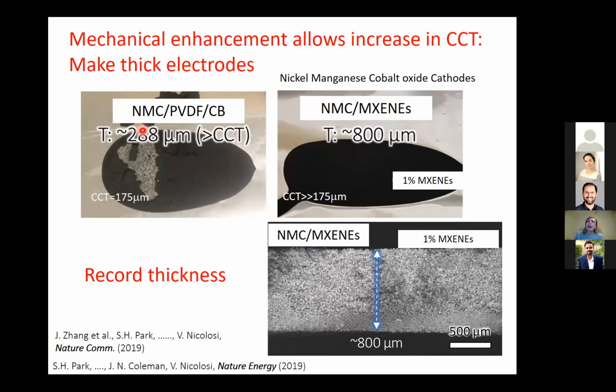So this is an example of some of the composites that we obtained, not only with the silicon, we also tried on the cathode side. Here is a conventional three-phase type of electrode. So NMC, cathodic material, polymeric additive, and carbon black to increase the conductivity. And here you can see that already at 288 microns, the film, the electrode, was starting to crumble. Basically, we were achieving a critical cracking thickness above which the electrode really doesn't support anymore the work it's supposed to do.